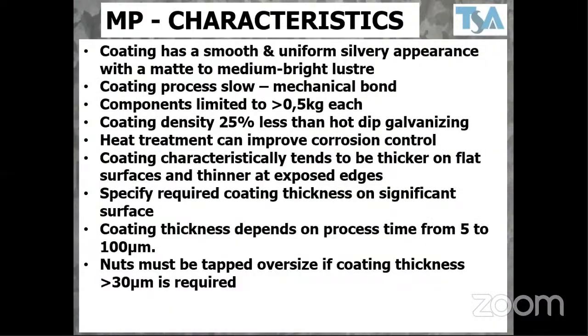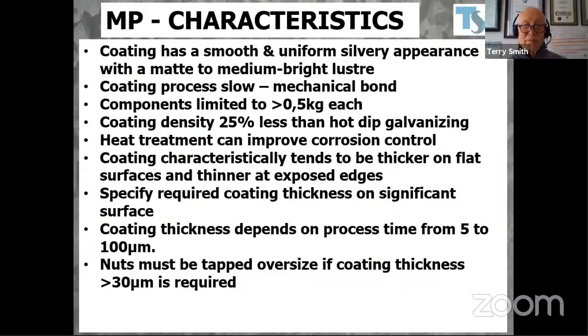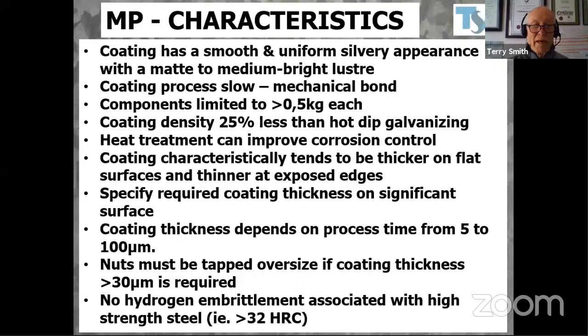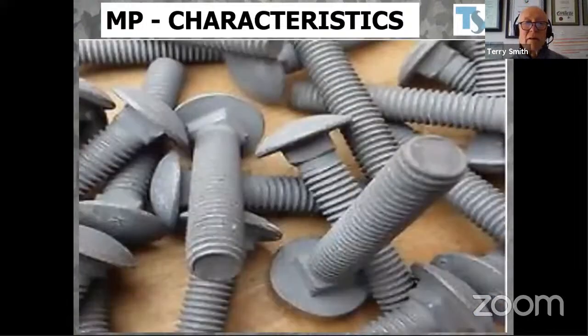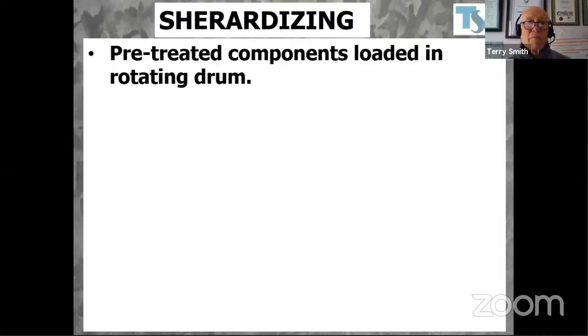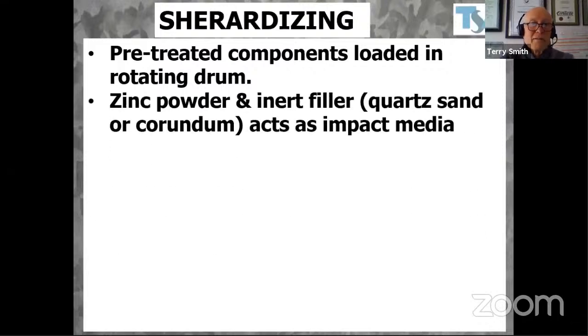Sorry. Okay, the nuts must be tapped oversized if coating thickness greater than 30 microns is required. And there's no hydrogen embrittlement associated with high-strength steel, which is Vickers hardness or Rockwell hardness of 32 and above. Sherardizing: pre-treated components are loaded in a rotating drum. Slight difference to this though, the zinc powder and inert filler, which is like quartz sand or corundum, acts as impact media.